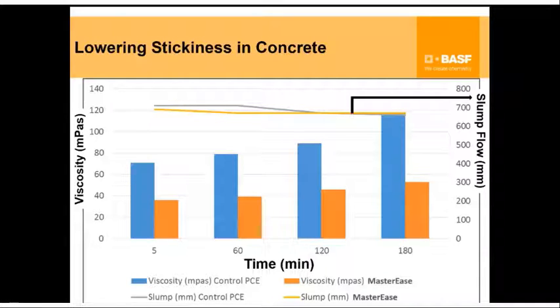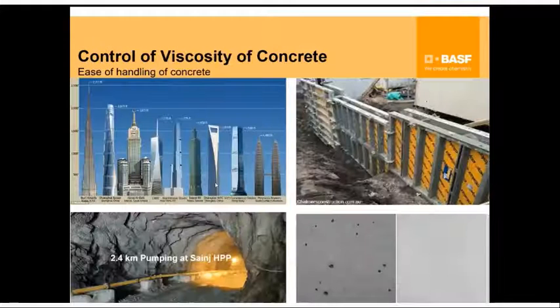Because of thixotropy, you will see an increase in stickiness. And so this is why the rheology retention is a very important characteristic that helps not only get a concrete of the right viscosity initially, but then it maintains that ability to pump and place over time. Next. So that shows the differential in viscosity over time.